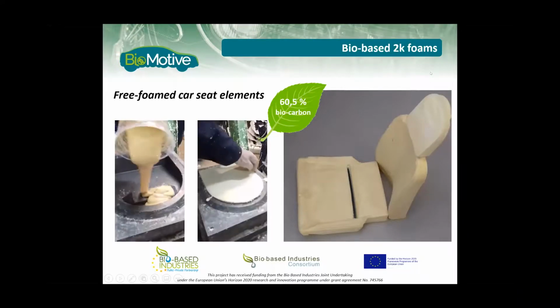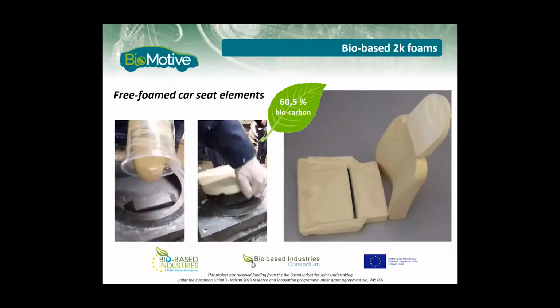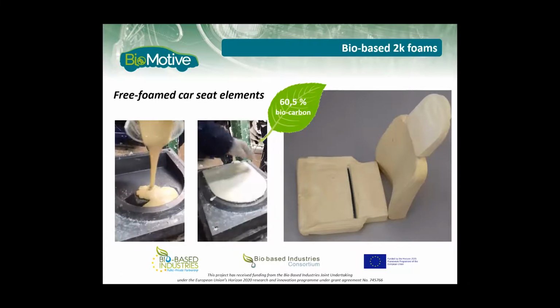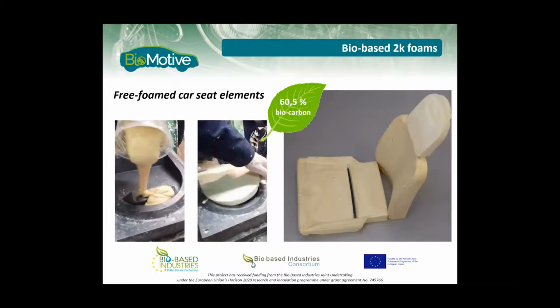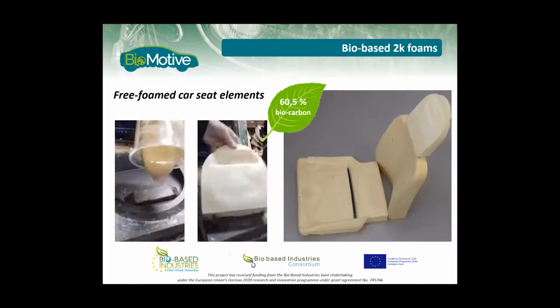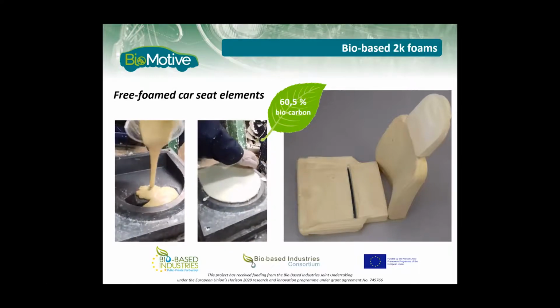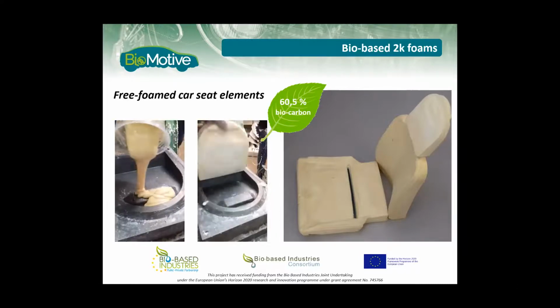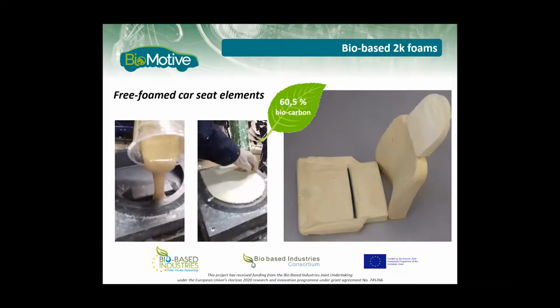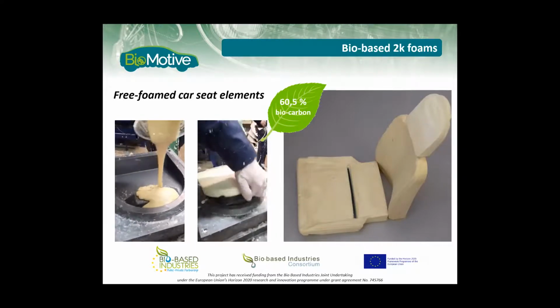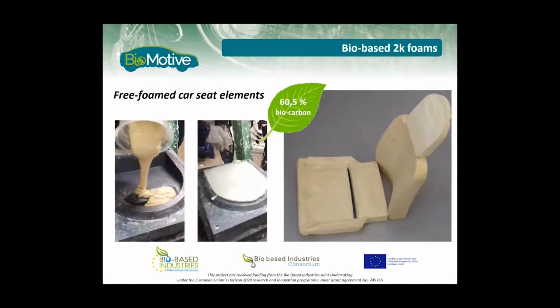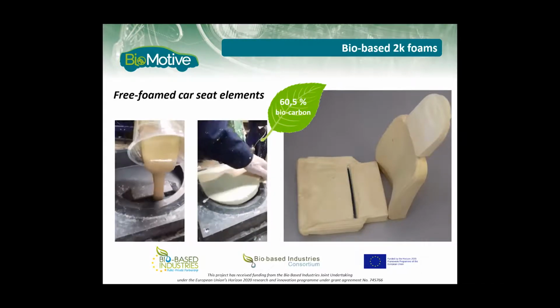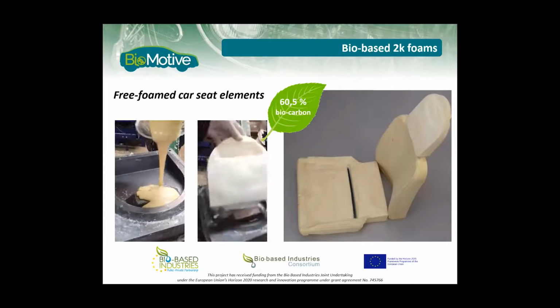We've managed to develop a formulation based on our biopolyols that gives a 60% biocarbon content within the foam. But of course, if you use cellulose fiber textiles to support the foam, to cover it with the foam with these fibers, you can get even higher. You can go even higher with the bio content.